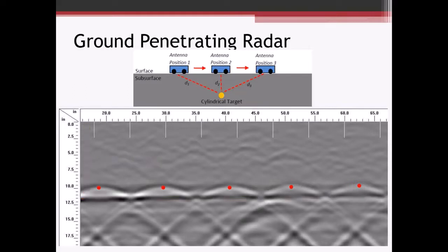You get that dark line right there, that's the slab thickness. It's about 12 inches. You can figure out what the concrete cover is. Concrete cover is about 10 inches here, which is pretty good concrete. One thing to note, the reinforcement's not on the bottom, right? How often do we see reinforcement, like a mesh, just sitting on the bottom of the slab? So at least that's not the case here.